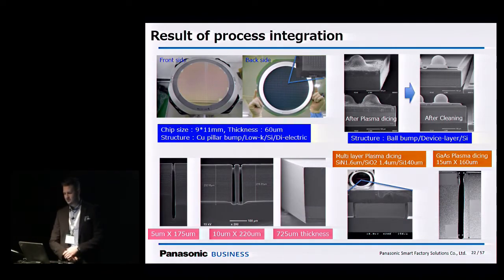And then these are some examples of the different situations we've diced in the past. So it's not always so easy for us to just get a silicon wafer and with nice, relatively wide dicing street, like 10 micrometers. Customers are always pushing us to do a more difficult application. So you can see a relatively large aspect ratio here, only 5 micrometer wide street width, but 175 micrometer depth. Also side by side here, but very thick is also possible for us. And multiple layers on the bottom right. Gallium arsenide also getting more common for us now in Europe. And if it's a 3-dimensional wafer as well, no problem for us to handle.